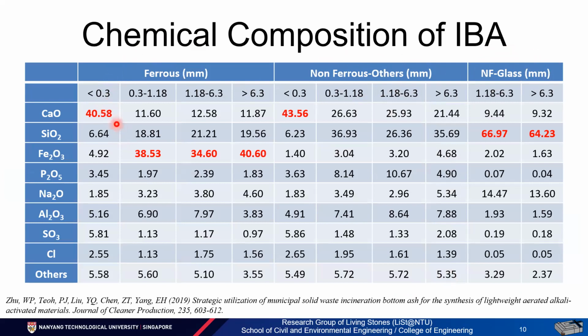For example, we found the calcium-based material was mainly concentrated at smaller particles, whether ferrous or non-ferrous. Whereas the silica-based material was mainly concentrated on the glass portion. Whereas the iron-based material was mainly focused on the ferrous portion, but that's mainly on the large particles.